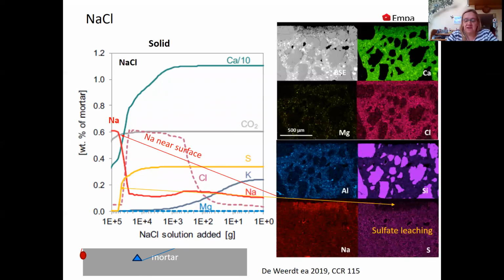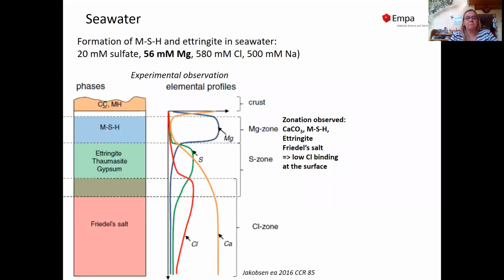If we compare it now with elemental mapping, we can see a very similar behavior. We can see sulfate leaching near the surface. We also can see the calcium leaching, which we both have predicted by thermodynamic modeling. And we can see an accumulation of sodium near the surface, which is probably related to the increased uptake of alkalis on the CSH, as well as to the possible formation of zeolitic precursors, which also bind alkalis.